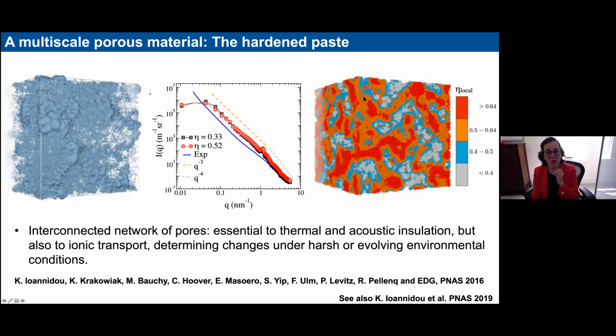And now from the simulation, just using the particle positions, you can compute the scattering intensity that you would obtain from this type of sample and compare it directly with experiments that are shown here. You can see the signal that you get, this upturn at low Q, that we obtain from the different degrees of heterogeneity that we have here. In fact, we can do more refined studies and see that this upturn comes directly from the presence of these pores, their connectivity, their shape and their surfaces. So we have some interesting indication that the structures that we have calculated in this way share very interesting similarities and structural features with the ones of the real material.